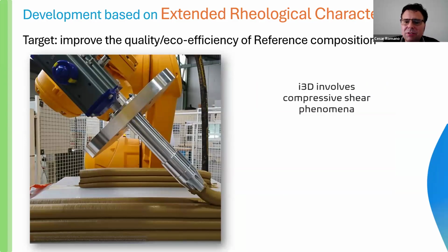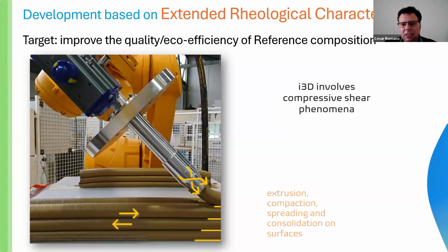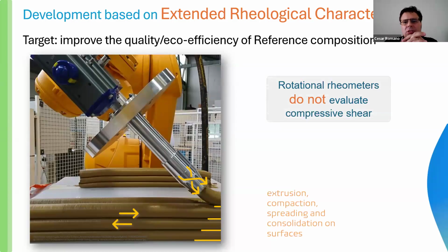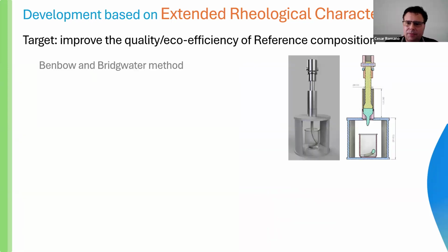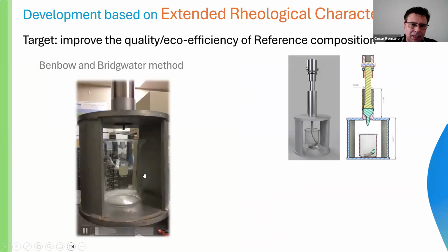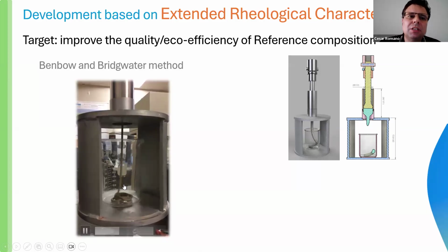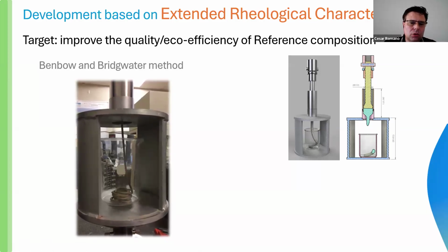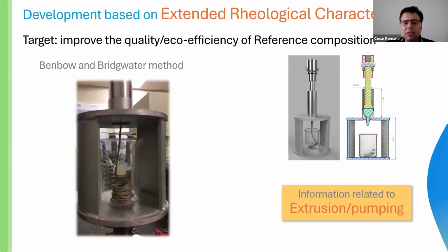But 3D printing involves compressive shear phenomena also, like extrusion, compaction, spreading, and consolidation on surface. And using just rotational rheometers, we don't have condition to evaluate the compressive shear. So to do this, we need to use another kind of methods. Benbow and Bridgwater was a kind of test where we are simulating the material when it is thrown by the nozzle. And during this process, it's possible to evaluate the extrusion pressure that we need for this deposition, for this extrusion. And we have information related to pumping and extrusion.